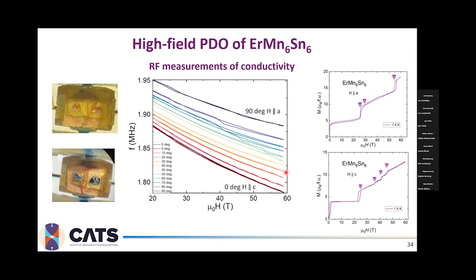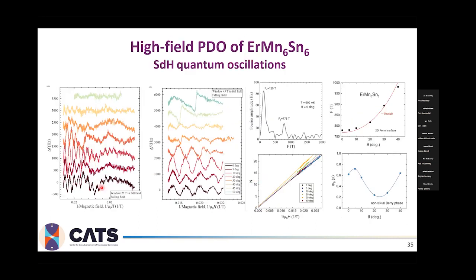I tried to investigate those quantum oscillations further and take the background subtraction, starting right above the first metamagnetic transition, 27 Tesla, to pick up maybe even some lower frequency oscillation. And there is also one just above 45 Tesla to focus more on the high frequency oscillation part. This also clearly shows us that when we are around 40 to 45 degrees, the signal is dominated by that sharp metamagnetic transition, and we are not able to see any of the quantum oscillation.